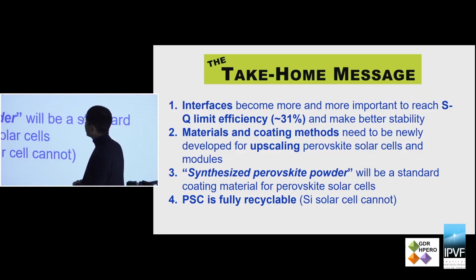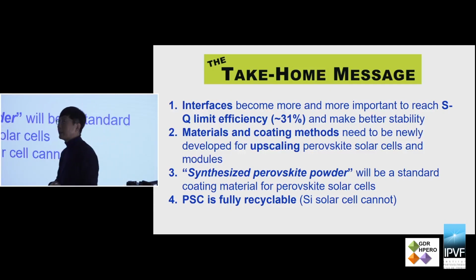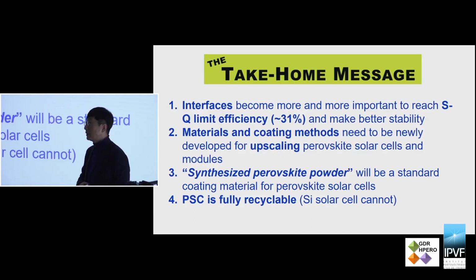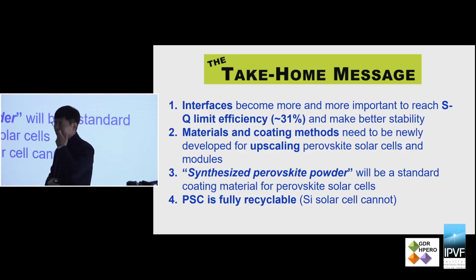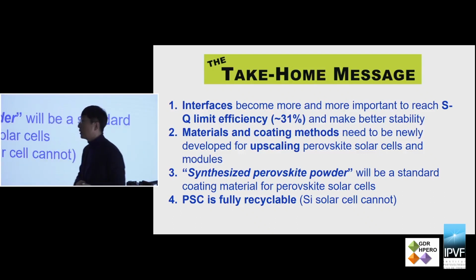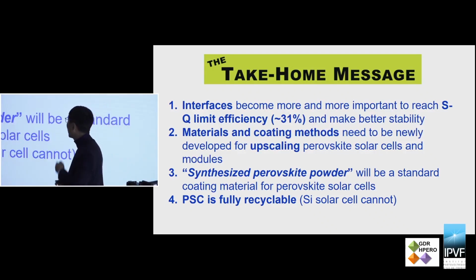And also the stability. We did some stability tests with encapsulation. We just took the technology from the organic LED for encapsulation, and we confirmed that there was no problem in the standard condition of 85 degrees C, 85% humidity. The device is still working after encapsulation. Still, we are using tin oxide, perovskite and spiro compound.